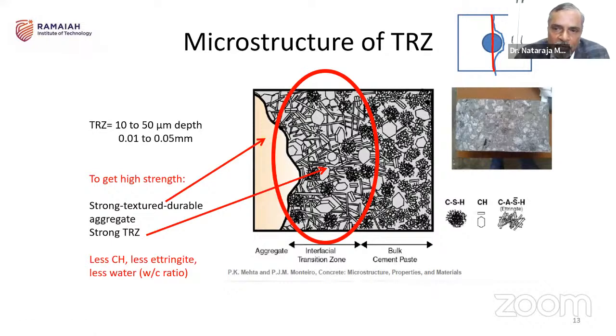And that is where the importance of the transition zone, especially in the high strength concrete mix design, comes into picture. Now, if you see here, the transition zone is just 10 to 50 micrometer in thickness. In terms of mm, it is 0.01 mm going up to 0.05 mm. And that is the zone which is holding the aggregate, and thereby the bond strength of the concrete is getting increased. It is not just the strength of the material; at some point in time, especially in case of high strength concrete, what is the load that really breaks the aggregate from the rest of the matrix? So the transition zone and its strength.